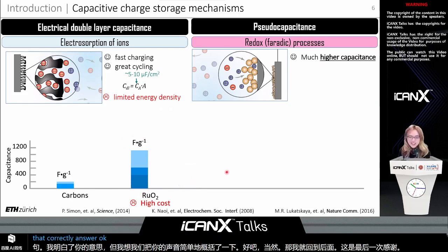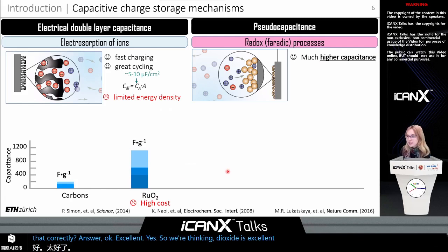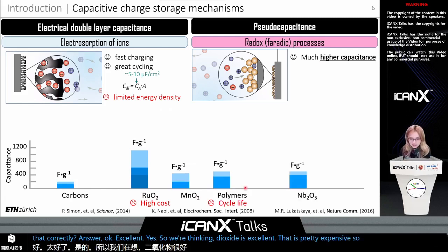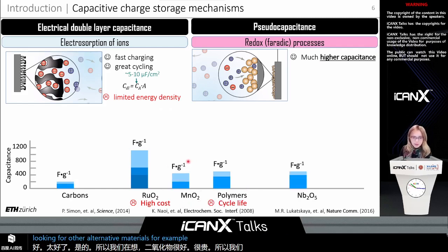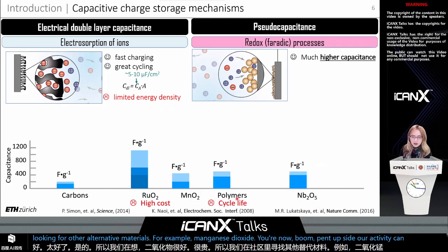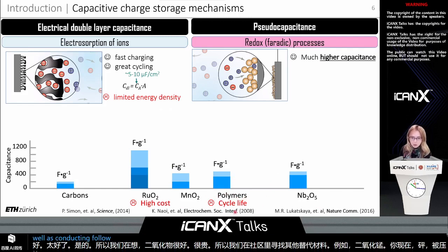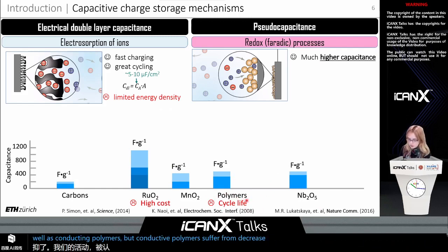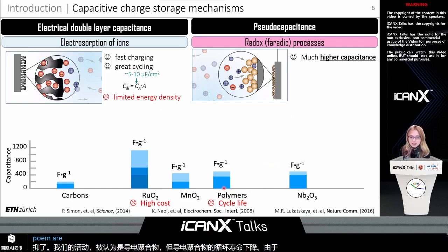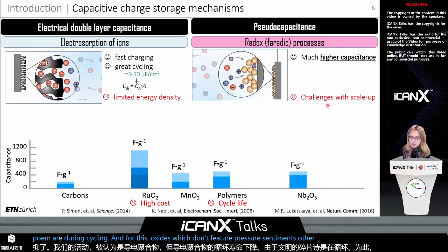Okay, excellent. So ruthenium dioxide is excellent, but it is pretty expensive. So we in the community are looking for other alternative materials. For example, manganese dioxide or niobium pentoxide are actively considered, as well as conducting polymers. But conductive polymers suffer from decreased cycle life due to solubilization of fragments of the polymer during cycling. And for these oxides, which don't feature precious elements, there are typically challenges with scale up.